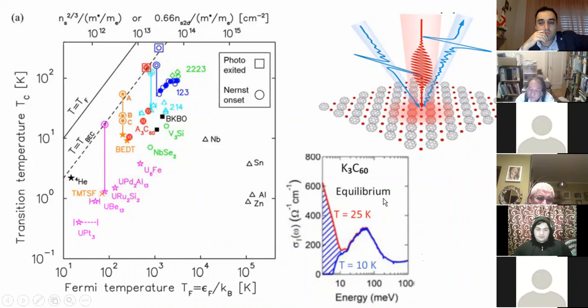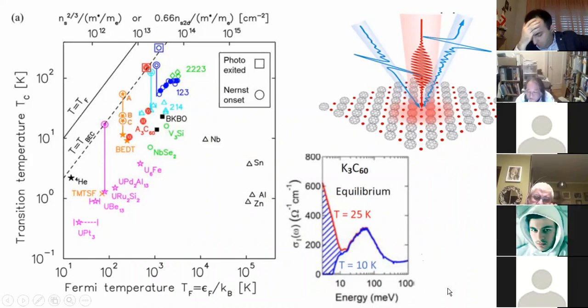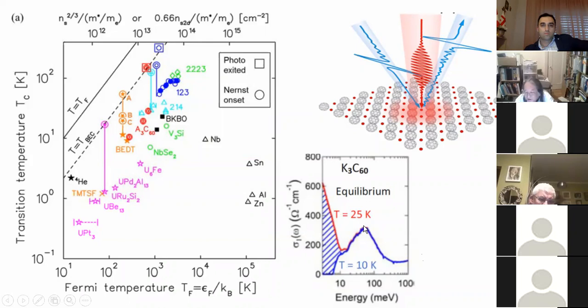And this equilibrium result shows what you measure without this red laser excitation. In a usual superconductor, what you would see in this kind of optical conductivity experiment is that in the normal state, without superconductivity at high temperature, you will see this red response. This peaking at low energy is called a Drude-like response, and this is typical of metallic material. But if you go into the superconducting state, then this Drude-like region is converted into a supercurrent. That means a delta function at a very large value at zero frequency, and so this shaded region would disappear. This is called the missing Drude weight, or a signature of superconductivity in the optical measurement.